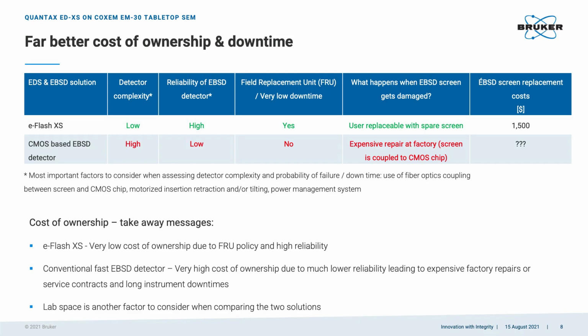Practically, we will ship locally a replacement unit within days, which the user can then swap with the failed unit by themselves. And also, what happens when the EBSD screen gets damaged, which can happen? Well, the user can immediately replace it with a spare screen when it comes to our XS system, while if you have a CMOS conventional EBSD detector, you have to ship the detector back to the factory for a very expensive repair, and that's because the screen is fiber coupled with the CMOS chip in the camera. So when you consider these important factors, and also a spare screen, it's $1,500. I don't know how much it will cost to ship to the factory and to have the screen replaced, basically. And also add to that the downtime. This would be a very, very much higher cost of ownership compared to the eFlash-XS solution.